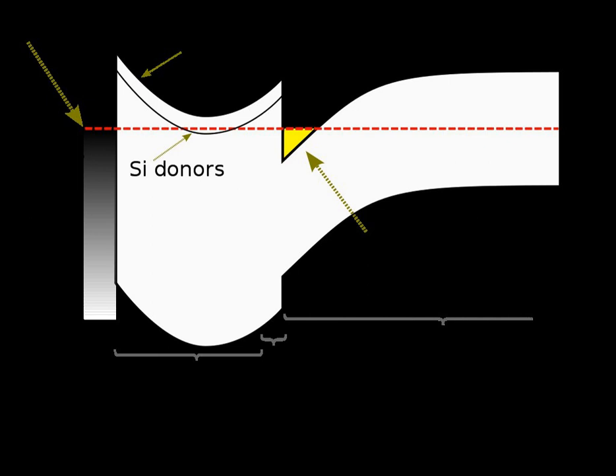MODFETs can be manufactured by epitaxial growth of a strained SiGe layer. In the strained layer, the germanium content increases linearly to around 40–50%. This concentration of germanium allows the formation of a quantum well structure with a high conduction band offset and a high density of very mobile charge carriers. The end result is a FET with ultra-high switching speeds and low noise.